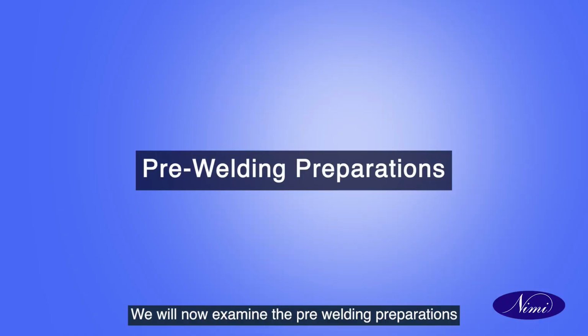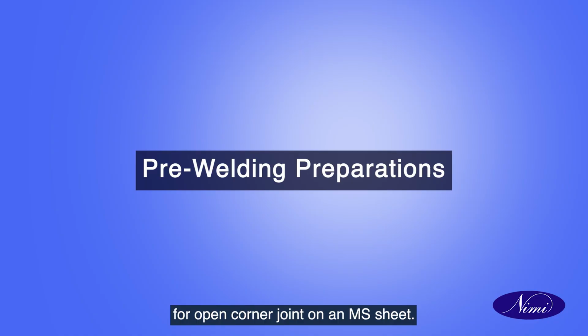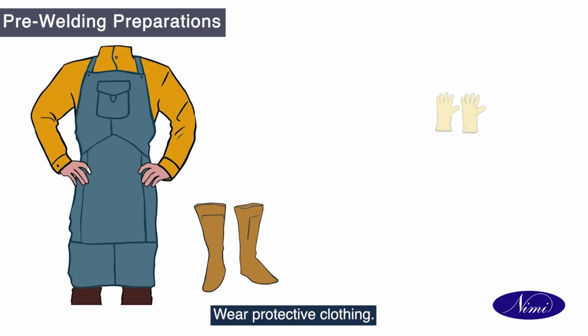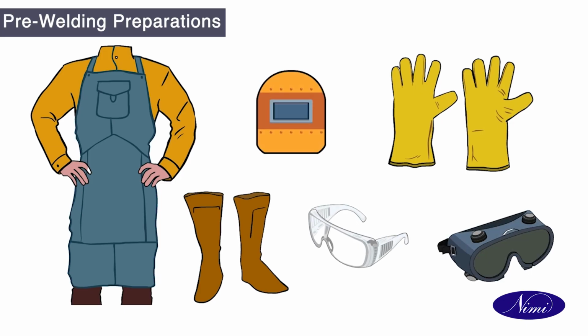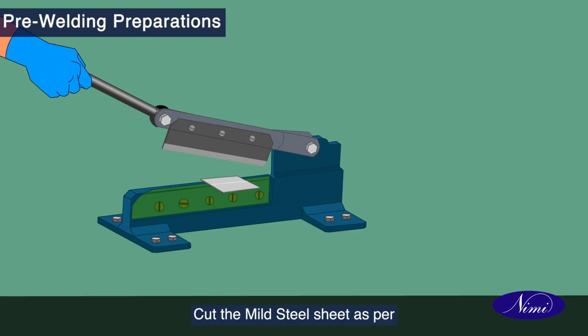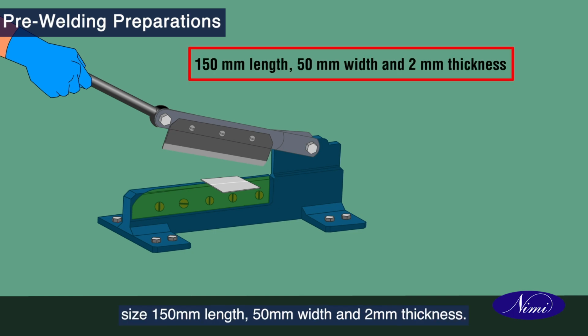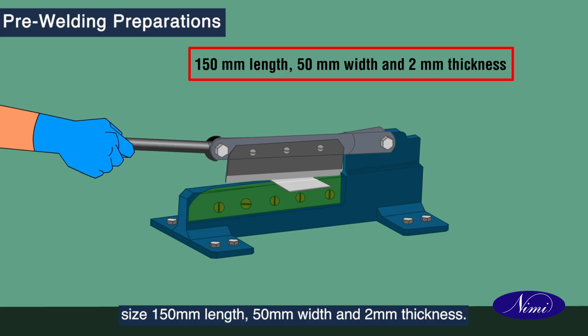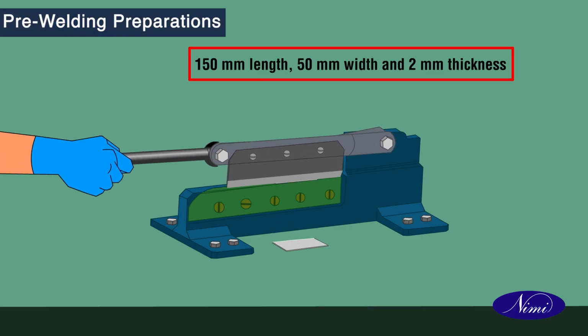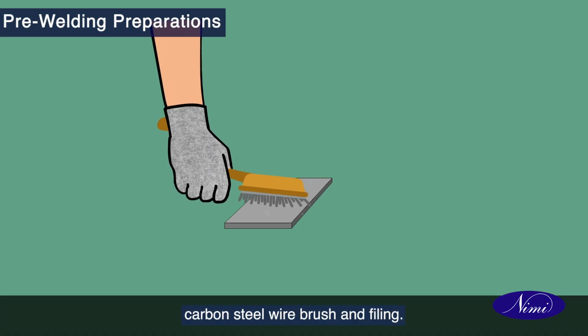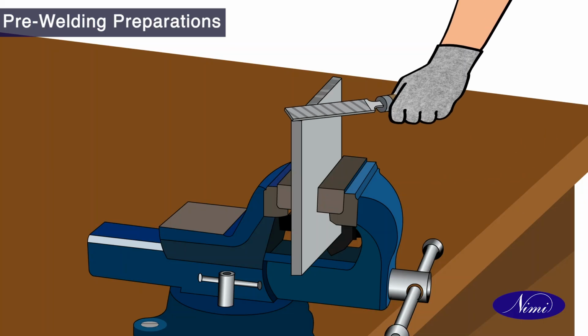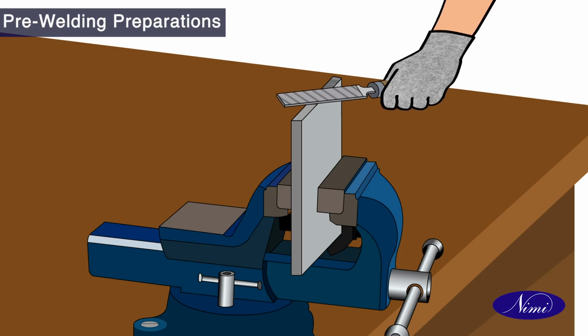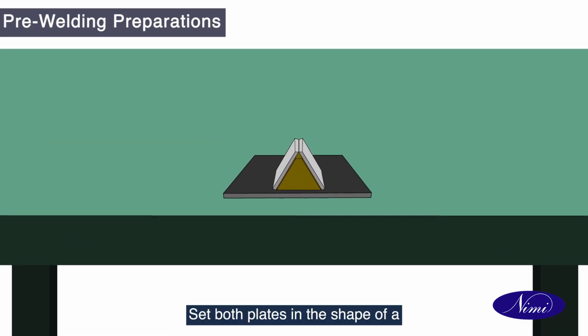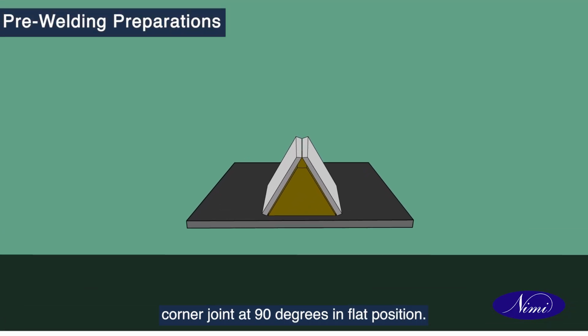We will now examine the pre-welding preparations for open corner joint on an MS sheet 2 mm thick in flat position using gas metal arc welding process. Wear protective clothing. Cut the mild steel sheet as per size 150 mm length, 50 mm width and 2 mm thickness. Clean the surface of the sheets by carbon steel wire brush and filing. Set both plates in the shape of a corner joint at 90 degrees in flat position.